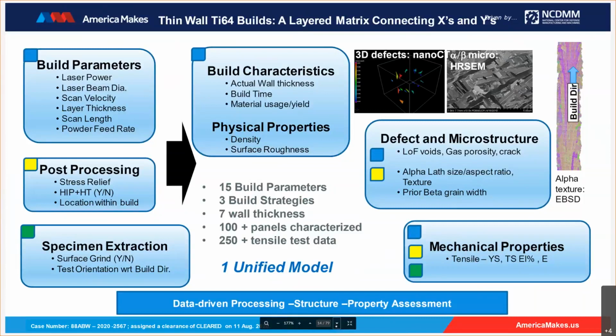That is intimately tied up with the mechanical properties that we find out in terms of yield strength, tensile strength, elongation, and moduli. So all this information, mind you, are in a quantitative fashion because these are basically the data that could be fed directly into the model.